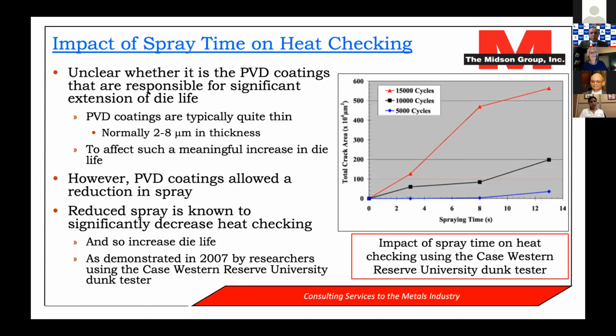So this begs the question, is it the PVD coating itself, or is it the reduction in spray that's allowing for this significant improvement in die life? And I think the answer is we don't really know yet. I'll give you my opinion. My opinion is that I think it's unlikely that it's the PVD coating itself. PVD coatings are typically quite thin, normally somewhere between 2 and 8 microns in thickness. And I think that's too thin to have a meaningful impact upon die life.